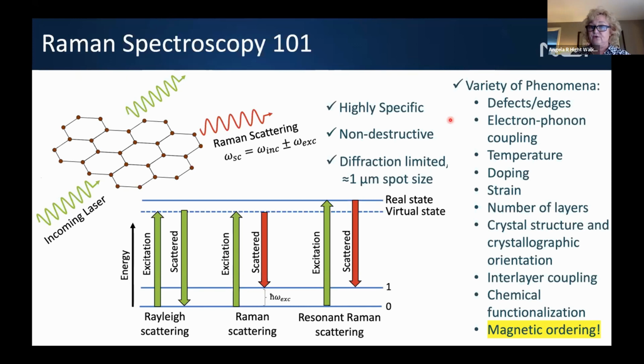So your spot size is on the order of a micron. Resolution can be under 500 nanometers. And then the rich information that Raman can tell you, particularly from 2D materials, everything from layer number to strain, as was mentioned. But today, I would like to tell you that magnetic ordering is also possible with Raman, and I'm going to give you 2 examples of that.